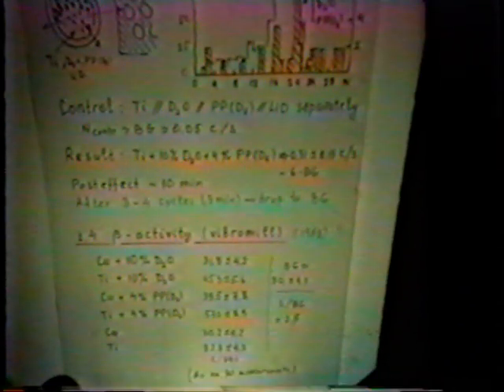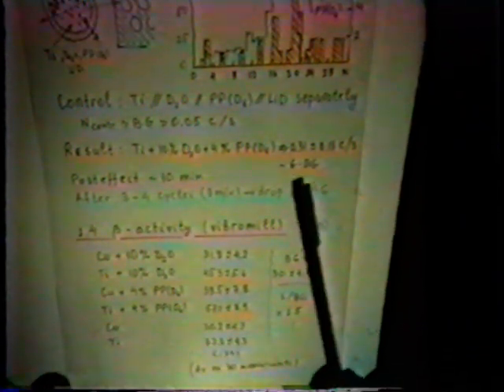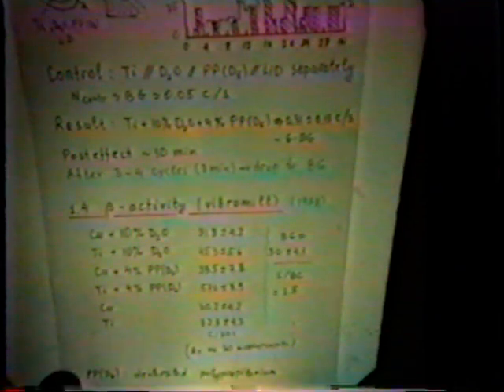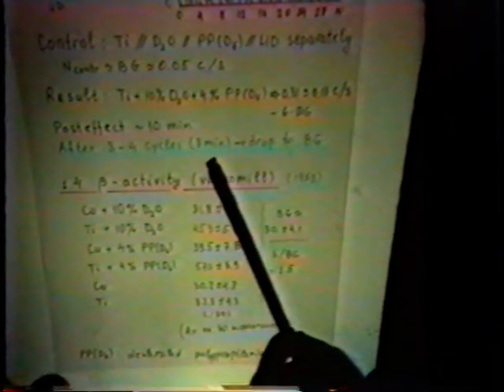And for this last case, the signal was about the background level. However, when they used the following combinations of material, they observed about 6 times the background level. And they also observed some sort of post effect for about 10 minutes after crushing was stopped. After 3 or 4 cycles, 3 minutes each, the signal fell to the background level.